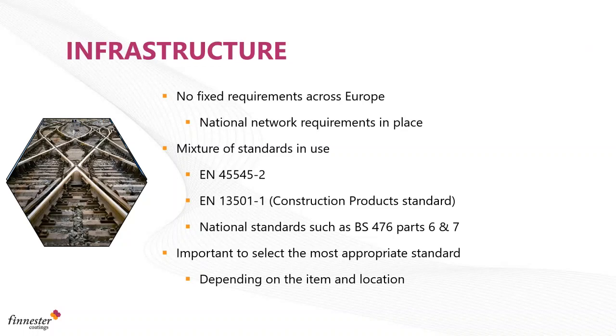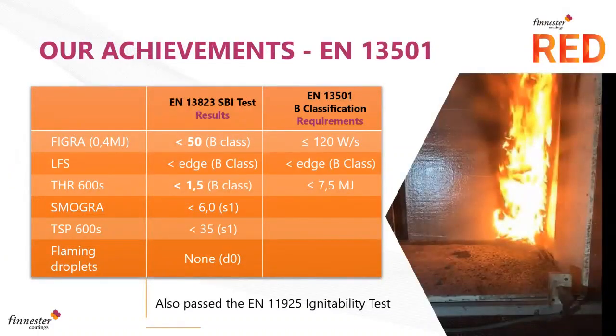What we've done here was the EN 13501, which we focused on a bit more, and there we've had some really very encouraging results. With the construction product standard, this is an A to E classification system. In reality, only incombustible materials will meet the A classification, so to expect composites to meet the A classification is really not going to be possible in most instances. So we fortunately are able to meet the B classification, the next best thing, which is certainly a lot better than some of the materials that are out in the market at the moment, which could be down at the D or the E classification. And you can see we meet the B classification very easily.